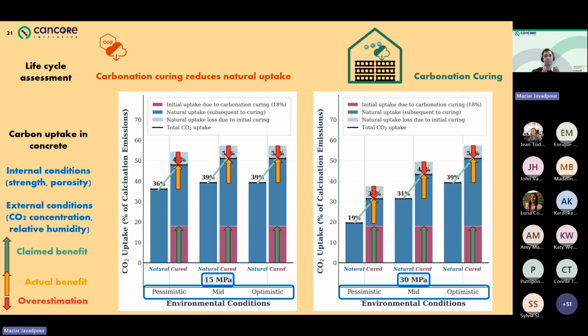If we take a look at these, we'll see that every one of them has two bar charts associated with them. One is natural and the other one is cured. And in every case, we can see that once we cure our concrete, we actually see an increase in the CO2 uptake, which is good. That's something that we want to see when we look at these utilization pathways.